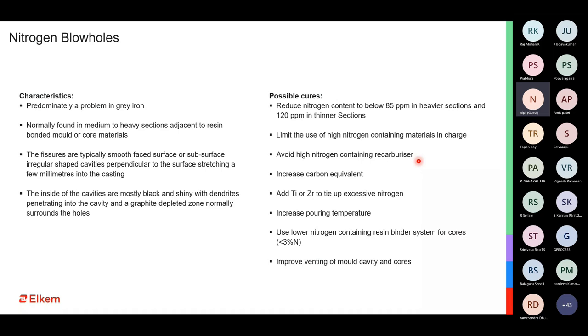Of course, we can also use titanium or zirconium to tie up the excessive nitrogen. Titanium as such does have its own problems. So titanium may not be a very feasible solution for nitrogen, especially in today's world where we do not want titanium in our system. So the other option could be to use zirconium. We have seen a lot of zirconium containing inoculants being used by foundries when they face this kind of fissure defect, but that's a solution to a problem which has already occurred. If we do not want the problem to happen, then a better way of doing it is to control the incoming nitrogen, which could be coming from the charge material or from the recarburizers.